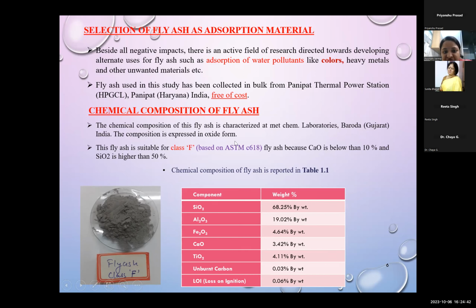Chemical composition of fly ash is characterized at Medchem Laboratories, Vadodara, Gujarat, and the composition is expressed in oxide form. From the composition study, this fly ash is classified into class F fly ash because it has calcium oxide below a low percentage and silicon oxide is higher than 50%.